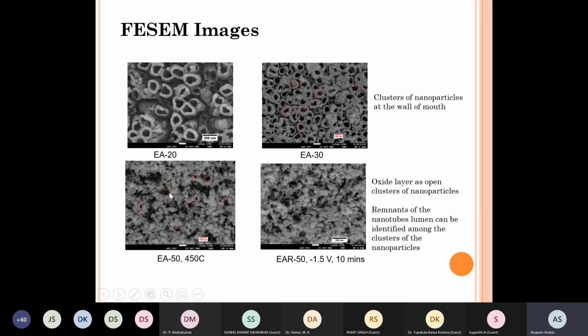If you go to 50 volts, then you can see that these are all dominated by these nanoparticle clusters, and you don't see much of the tube geometry here, but all of these lumen that you see are remnants of these tubes. So if we go to higher voltage, first the tubes are formed, then these nanoparticle clusters are formed. So you still get lumen which are more or less straight, but now you get rough boundaries of these lumen and therefore more surface area.